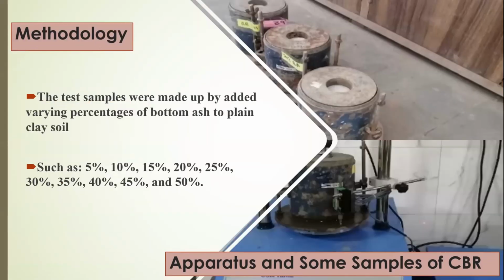This is the methodology. Samples were prepared by adding different percentages of bottom ash to the clay soil, such as 5, 10, 15, 20, 25, 30, 35, 40, 45 and 50%. In addition, there are two standard samples: one of clay soil only and one of bottom ash only.